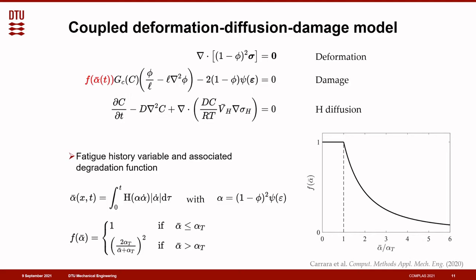And finally, we incorporate the effect of fatigue damage into the modeling framework. And this is done by introducing a fatigue degradation function, which effectively modulates the fracture toughness of the material as a function of the fatigue history experienced by the solid. And the fatigue history variable, alpha bar, is chosen as a cumulation of elastic strain energy stored in the solid,